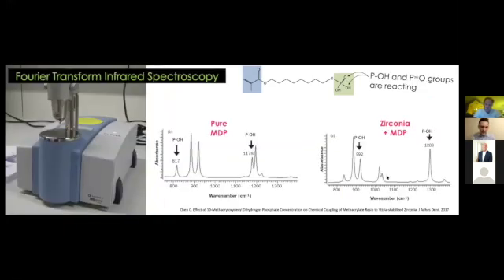The next evaluation that was done was something called Fourier Transform Infrared Spectroscopy, or FTIR. What this test does is they take these infrared beams and pass them through bonds of material, and they vibrate at certain activity levels. Essentially, it shows you which bonds in a molecule are active. So they took some pure MDP molecule, they looked at it under FTIR, and they found where the different functional groups, or different side groups on this functional group of the MDP are,